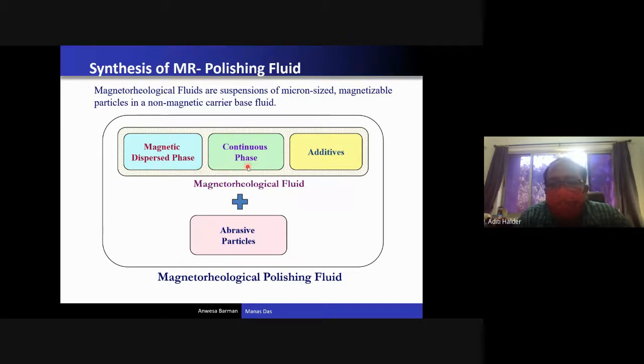Another problem is agglomeration of these iron particles. When you apply a magnetic field, these iron particles form chains. In the agglomeration problem, what happens when you remove the magnetic field? There is a remnant magnetization present in the iron particles. Because of this remnant magnetization, they remain a little bit magnetized although you remove the magnetic field. So these iron particles come closer together and make bigger size particles, and the abrasive particles get fixed in between them. These bigger size particles, instead of finishing, will remove bigger size debris and chips from the workpiece surface. So instead of polishing, they will do a machining action, which we don't need.